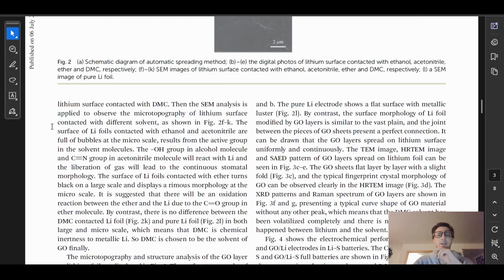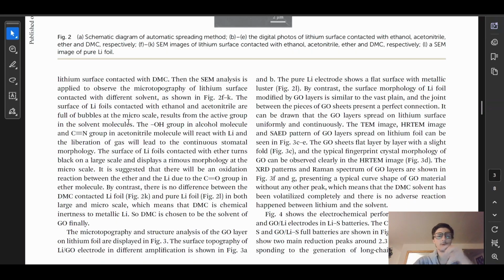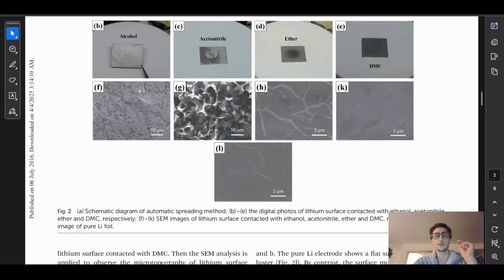Then the SEM analysis is applied to observe the microtopography of lithium surface contacted with different solvents as shown in figures F through K. We already saw those. The surface of lithium foils contacted with ethanol, acetonitrile are full of bubbles at the microscale. That's exactly what I said, little bubbles, tiny bubbles. This one actually looks like bigger bubbles than this one.